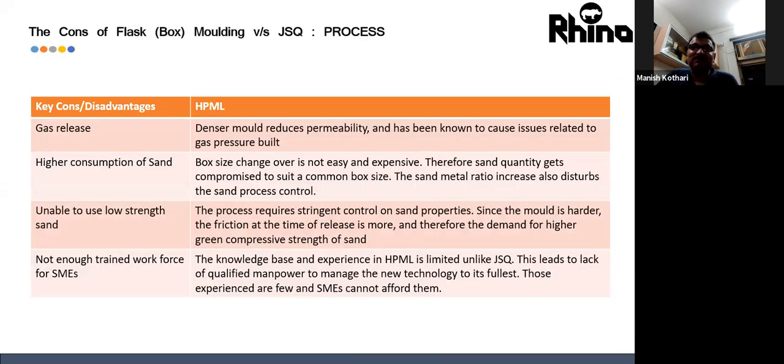At the same time, there are some disadvantages which we have found, and particularly, imagine that this is a denser mold, so the release of gas will be more difficult. This I think the foundry process people can explain much better, but I've seen the entire sand cake lifting in the box if the venting or gas escape is not good, and this causes casting shift due to process.